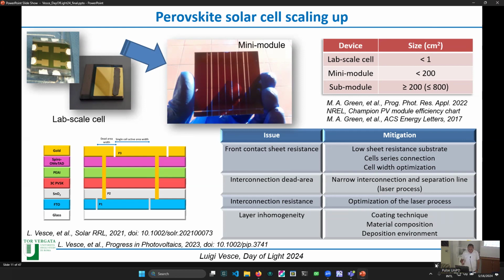One should optimize the interconnection such that the dead area width is as small as possible, because it's something that doesn't generate any current. And then you have the single cell active area width. So at the very end, I anticipate some issues in the upscaling process. The first one is the front contact sheet resistance that is related to the conductive substrate. That's why, to mitigate this, one has to choose a low sheet resistance substrate. Generally, we work with substrates of 7 or 10 ohm per square. And then optimize the cell series connection, the cell width optimization.